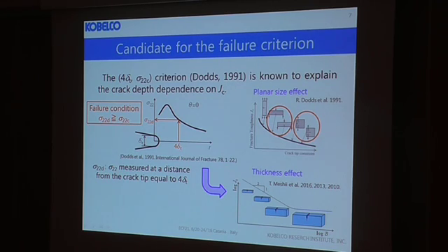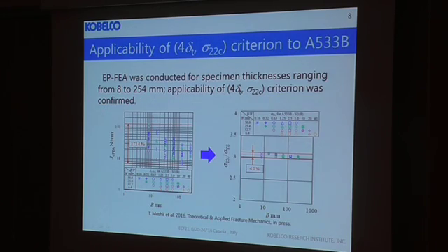This criterion was validated as explaining the crack depth dependence on JC by Dodds et al., and test specimen thickness effect on JC by Meshi. Through examination of the applicability of the 4δt σ22c criterion to decommissioned RPV steel JC database with specimen thickness ranging from 8 to 254 millimeter, Meshi showed that although the variation of JC was very large, the variation of σ22c was very small, approximately 4%.